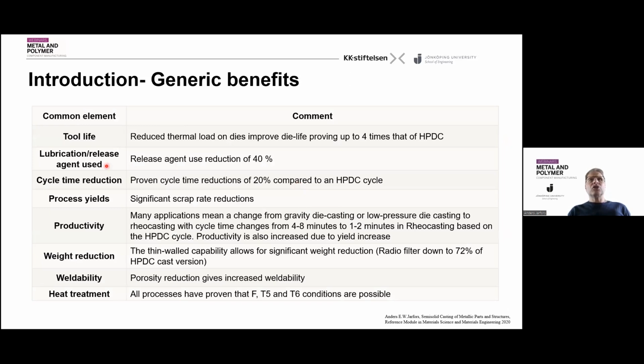And when you look at the reduction of heat load, thermal load, that means that the first thing that happens is that die life goes up. So you get better die economy. And then you need to use less release agent. And this is actually something which is very, very important, because what drives defects is actually release agent emissions and atmosphere generated in the tool. And this is actually very, very important when you're going to cast larger components. So this is a process issue that we need to work with. And that is something that is critical to what we are working with.